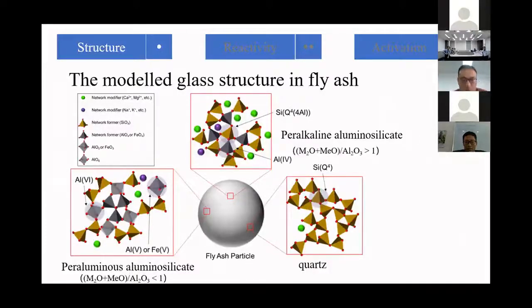It can be simply ascribed as 3 different parts of glass. The first part is the peralkaline aluminosilicate glass. The structure is similar to that in slag. And the second, this is the most reactive part of the fly ash glassy phase. The second glassy phase is the so-called peraluminous aluminosilicate. The aluminum is 5 or 6 coordinated because of the lack of cations in these structures, and this reactivity is weaker than alkaline aluminosilicate. And the third kind of glass structure is the quartz-like glass structure. For this phase, the reactivity is quite low.